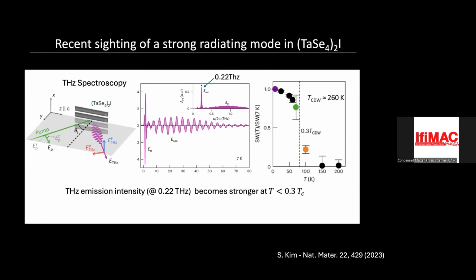This is the experimental observation: you measure the intensity, the height of this peak, as a function of temperature. The charge density wave transition happens at high temperatures, like 220 Kelvin or something like that. I can't remember, some 200 something Kelvin. Does it say here? No. 260 Kelvin. But at some other funny temperature of 0.3 times T_CDW, which is around 80 Kelvin, you can see the intensity above that temperature is really low, actually 0. But as soon as you hit this temperature, the intensity sharply rises and then saturates. So the sharp rise in intensity is basically a signature that this thing is a massive phase mode.